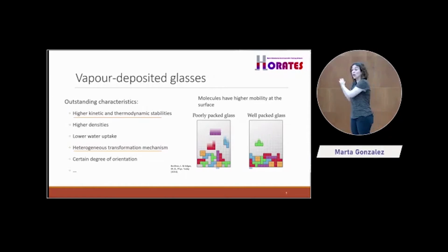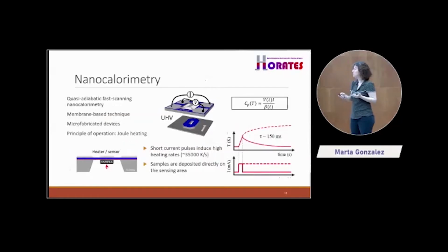So we want to do calorimetry on these films, but we have a problem. If we do conventional calorimetry, the ones that I was showing, we're not going to see anything with a nanometer size film and such a small amount of energy exchange. So we need a special technique. And that's why we're using nanocalorimetry. Nanocalorimetry is a technique that was developed in the world in several places, more or less at the same time. One of these places was the research group where I'm working. And it's a very special technique because it allows you to do calorimetry with thin films, with samples that are really, really small.